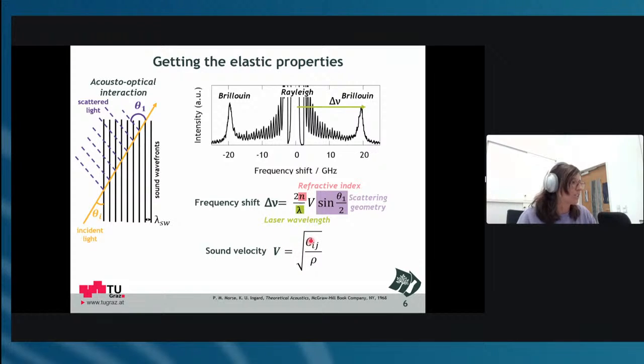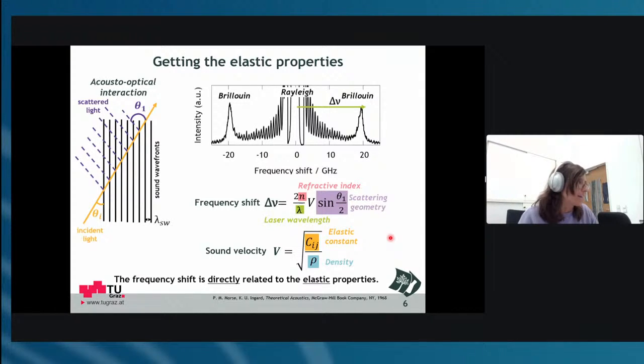relating the sound velocity to the stiffness in your material, or your elastic constant if you have an anisotropic material. And this is only connected via the density of your material. So when you investigate a specific material, if you know the refractive index and the density of the material, you get everything from the measurement, because you know the geometry that you are using and your laser wavelength. And nice about this method is also that this frequency shift that we measure here, these 20 gigahertz, is directly related to the elastic properties of your material. There are no assumptions. I don't say, okay, this is like in a tensile test, this area is linear elastic, and then I do the fit there, or in nano indentation, where you have an indentation curve and then you have your contact model and assume certain things. Here, at least for this, it's a direct relationship.